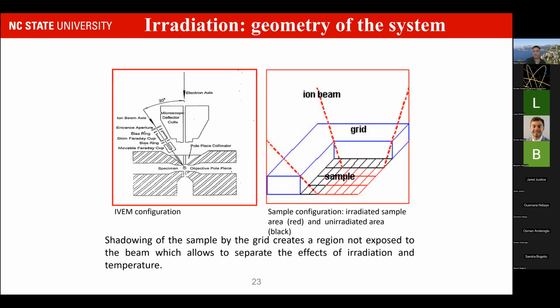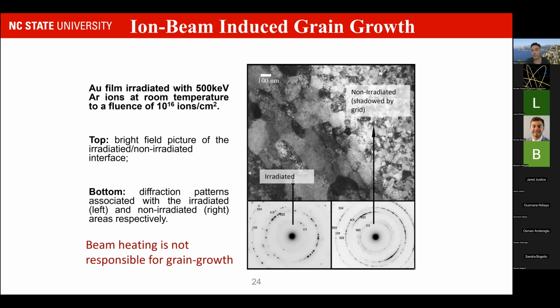Another aspect that also helped in the experiments was the geometry of the experiment. We were using samples upside down with the TEM grid on top of the sample. Because of the thickness of the grid and the fact that the ion beam was coming at a certain angle, about 16 degrees, we had systematically a region very close to the TEM grid that was shadowed by the grid and therefore was not hit by the beam. So for each experiment, without having to do any covering or any special trick, except for looking at it upside down, we were able to have information on the region irradiated at the center and the non-irradiated region right nearby.